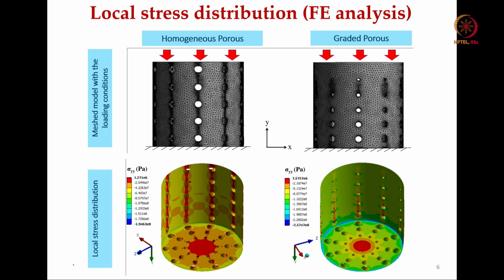This shows more results on the analysis of the stresses around the pores. As you saw in the earlier slides, in our finite element model around the pores, this is the uniform pore size, right, and around the pores the mesh concentration is increased to capture a more realistic distribution of stresses. For the same 3D reconstructed images, when you consider the von Mises stresses, the local stress distribution around the pores, sigma yy is in Pascal. It is 10 to the power 6, so this is megapascal. It is 1.3 megapascal.